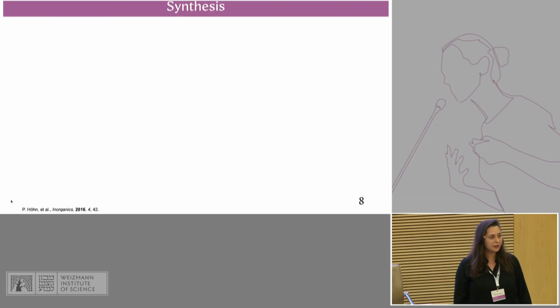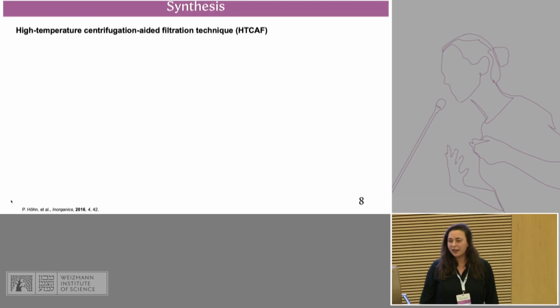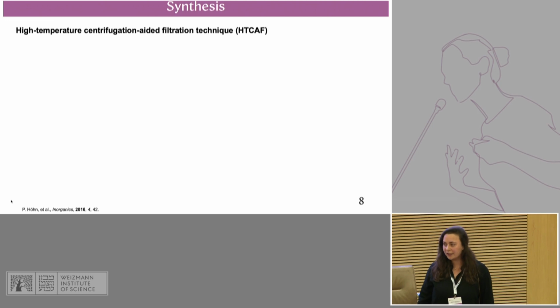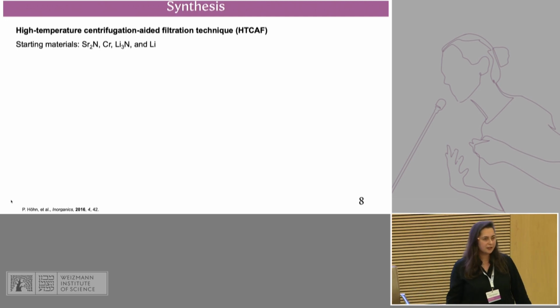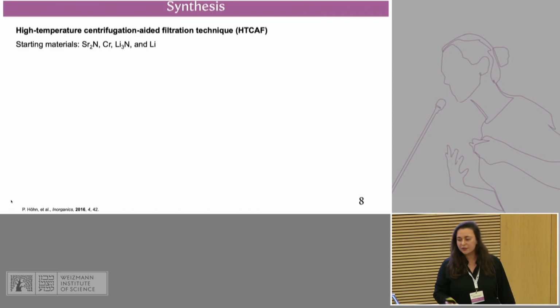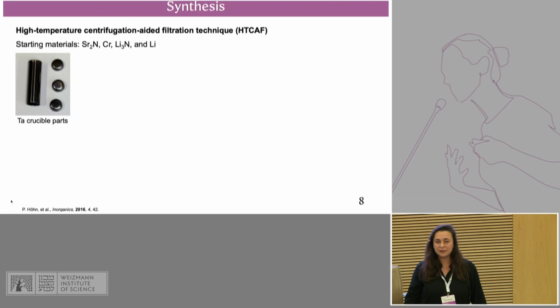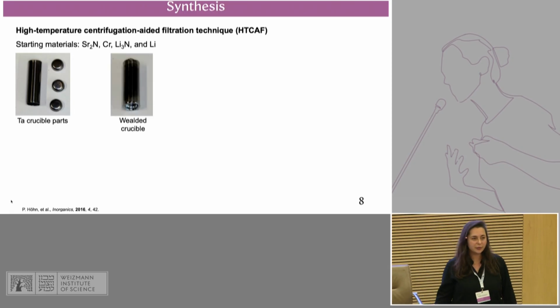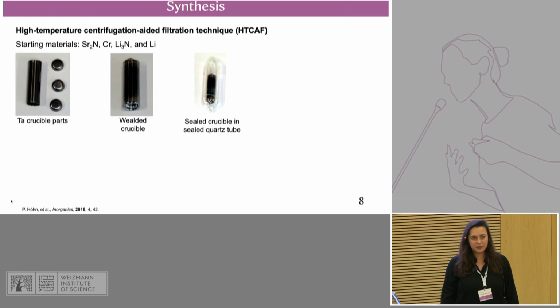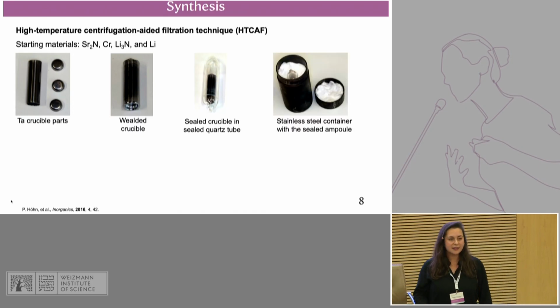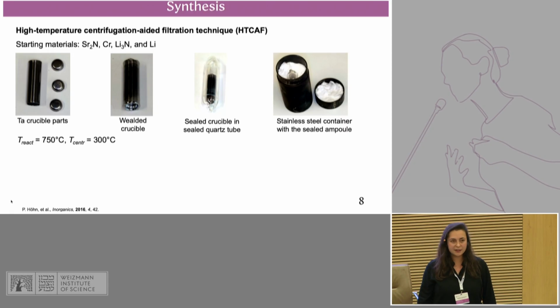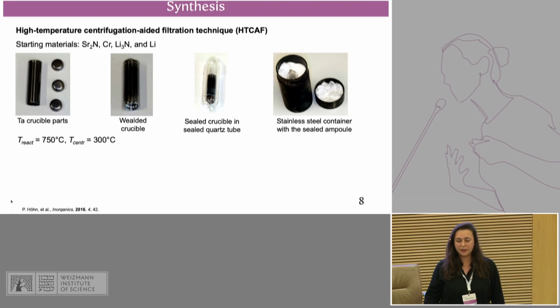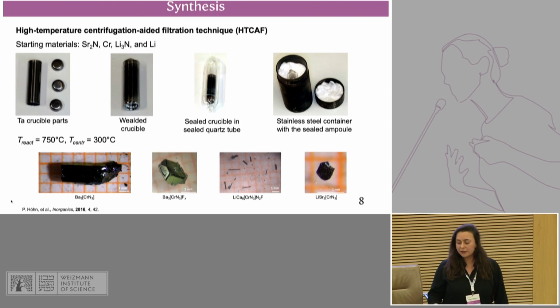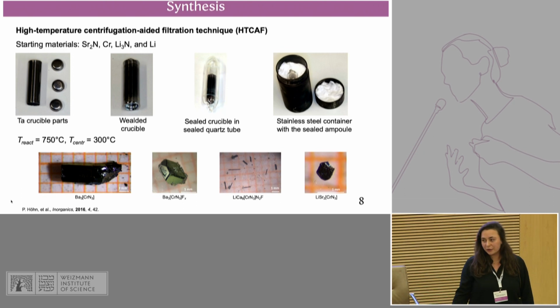To answer this question, we started with synthesis, and we used a high-temperature centrifugation-aided filtration technique. We started with starting materials, binary nitrides, chromium, lithium, mixed them together, put them in tantalum crucibles, welded these crucibles shut, sealed them in quartz tubes, placed them in stainless steel containers, heated up the system to elevated temperatures, held it, cooled down to 300 degrees, and centrifuged to separate crystals from the flux. As a result, we were able to synthesize nice crystals.